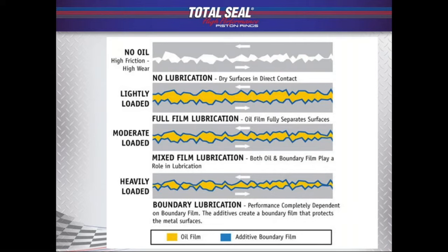About 90% of the failures that I see, customers sending me rings, almost always come down to some sort of a lack of lubrication to the part. The ring itself is really a pretty simple piece. If I make it round, I make it flat, I make it light tight, I make it the best I can possibly make it, I really can't do more with that part. So if I put the part into an environment where I've got an excessive amount of fuel, I don't have that lubrication of the part, that oil film that creates that gasket, that sealing surface between the ring and the cylinder wall, we're going to have that failure. And I get the part in and I look at it, it's simply a lack of lubrication of the part. There's a lot of things that can do that to the ring, but getting that cylinder finish right for that application is so important. It's the first step to eliminating that issue.